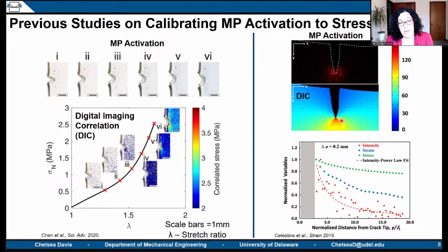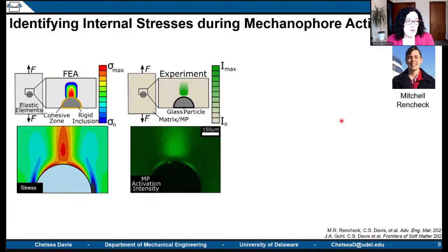That material, while you can extend it quite significantly, is also really brittle if you get a notch in it. So it can fail brittlely, and the crack will propagate in an unstable way once you notch that material, making it really hard to keep looking at the crack tip. So when my first PhD student joined the lab, we thought, well, is there another way to concentrate stress within a composite material? So what Mitch Renchek did when he first joined the lab was rather than focusing at the tip of a propagating crack, he chose to focus on the poles of a rigid inclusion.